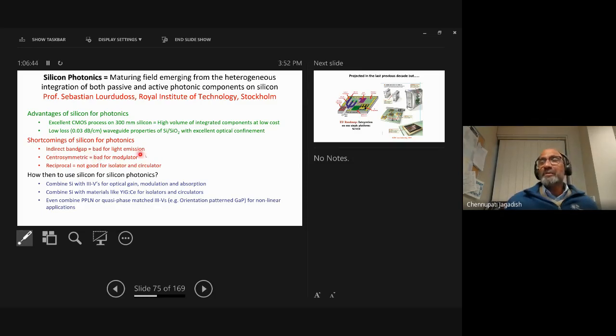But at the same time, people have tried. Richard Soref is the one who demonstrated that by changing the carrier concentration in silicon, you can change the refractive index of the medium, and then use that for modulation applications. And nowadays, by putting the silicon into a cavity, allowing the light to interact with the medium much more often, and by having high Q cavities, people are able to show very highly efficient and high speed modulators. In fact, Intel is now manufacturing these, for example.